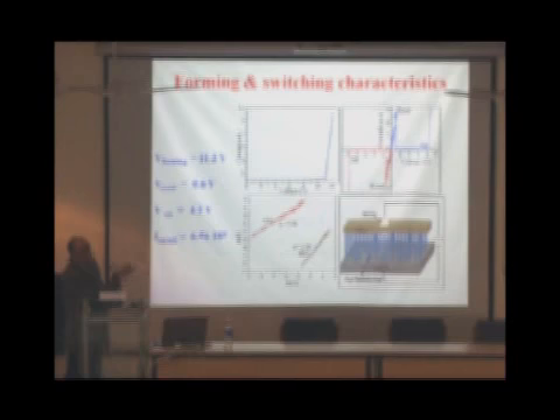This is the forming. On application of around 11 volts, the device goes to an electroformed state, and then the IV characteristics are this. On application of this voltage, you go to the set state and you can go back and forth. What is important is the on and off current ratio. The ratio of the current in this state and this state is something like 10 to the power 4, which is very high. This is one of the advantages of this kind of device, that the difference between the on state and off state in terms of the current or in terms of the resistance is very high.